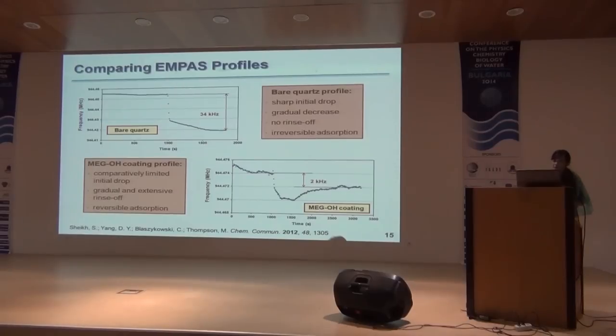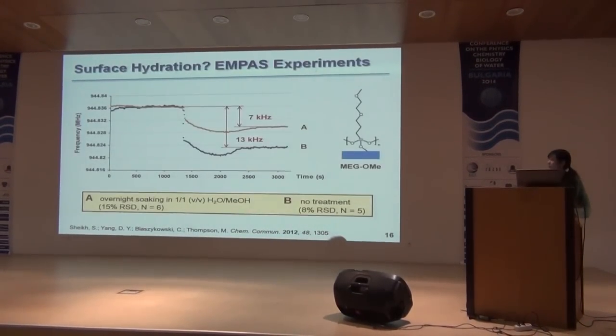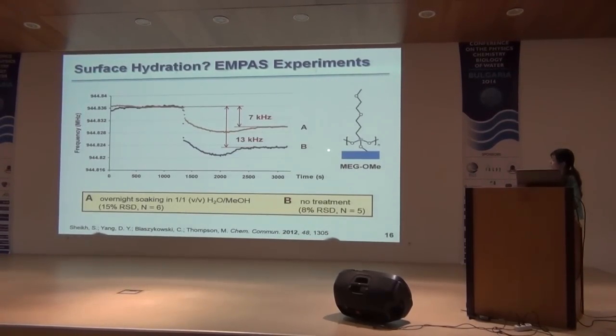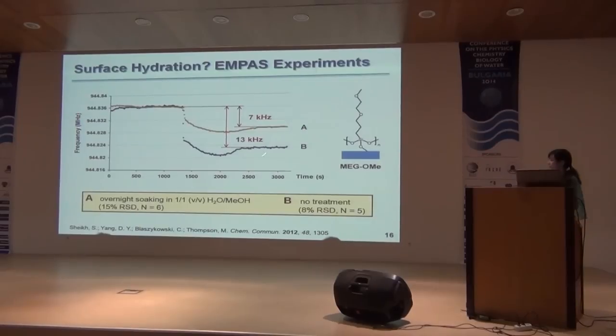We were able to show that our coating decreased non-specific adsorption of serum species. Reading the literature, we came across the important role of water in antifouling. So we tested our surfaces by comparing a dry state versus an overnight water-methanol treatment. For MEG-OMe — which has the internal ether oxygen and an O-methoxy group — the hydration treatment reduced the frequency shift from about 13,000 to about 7,000 Hz, confirming that water plays a role in surface hydration.